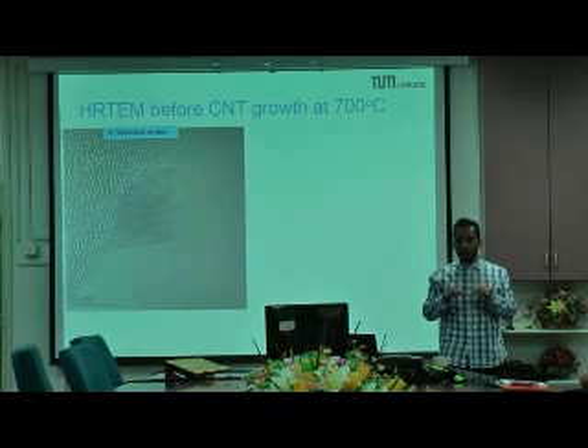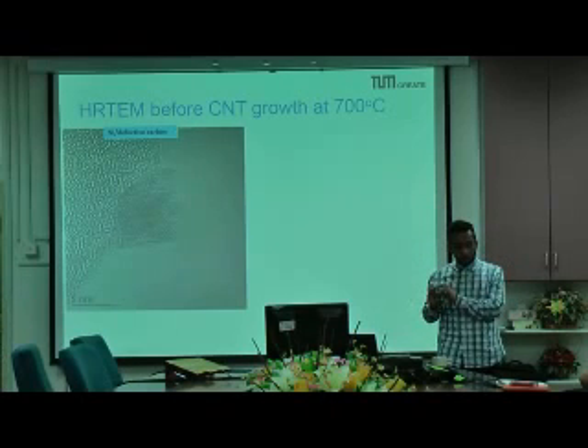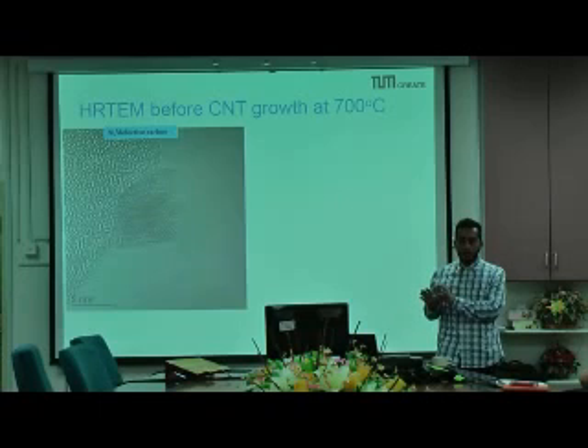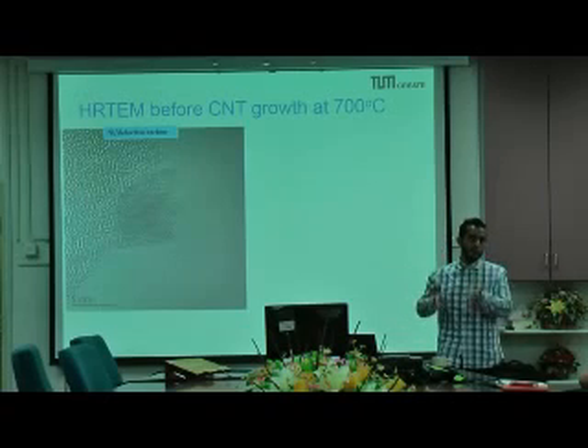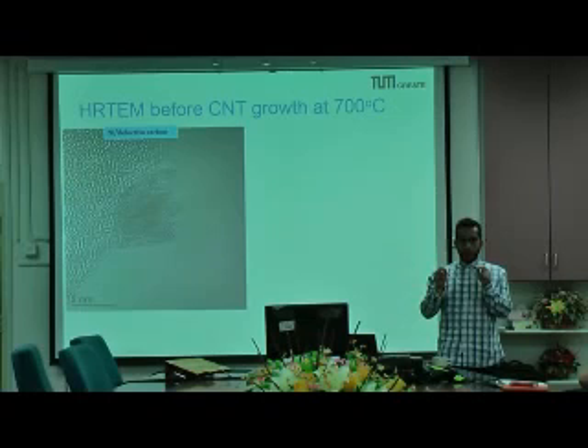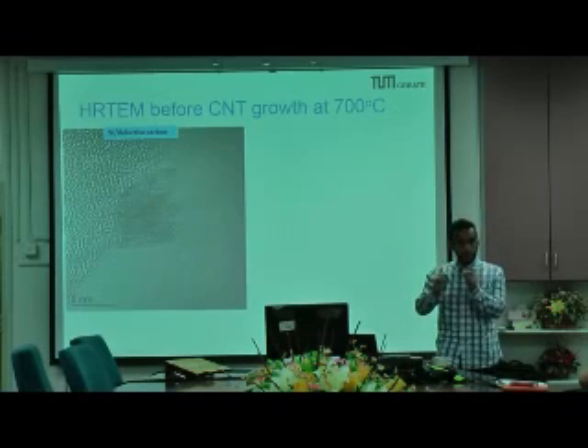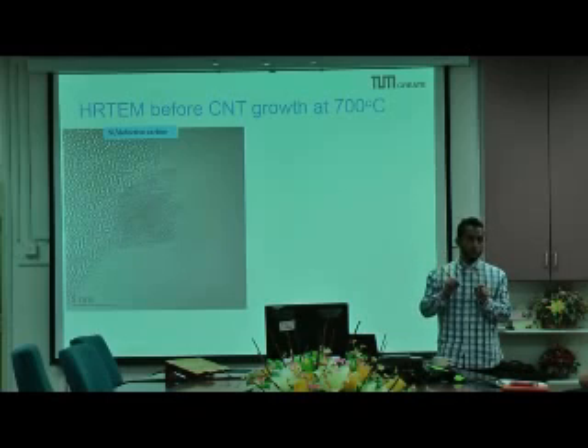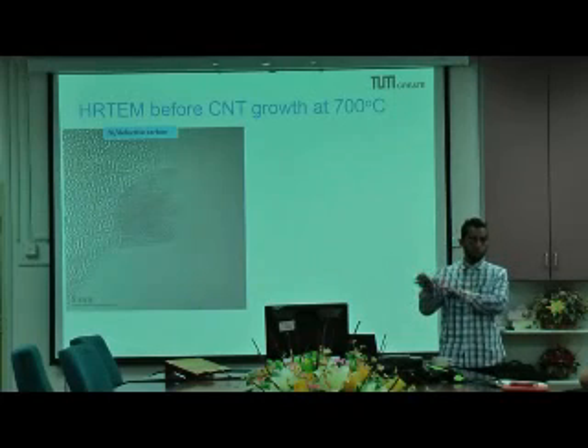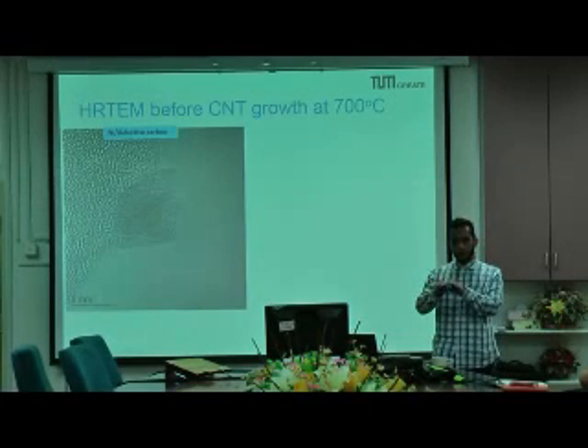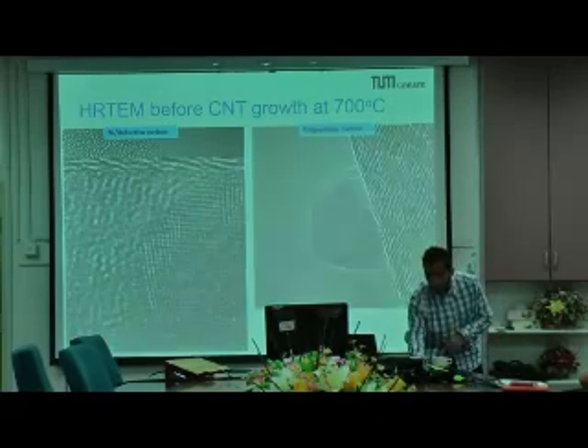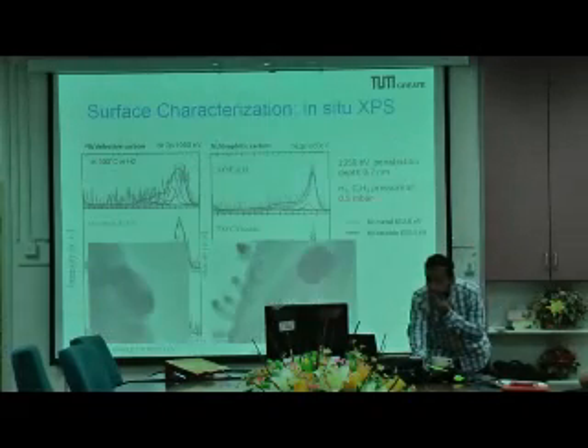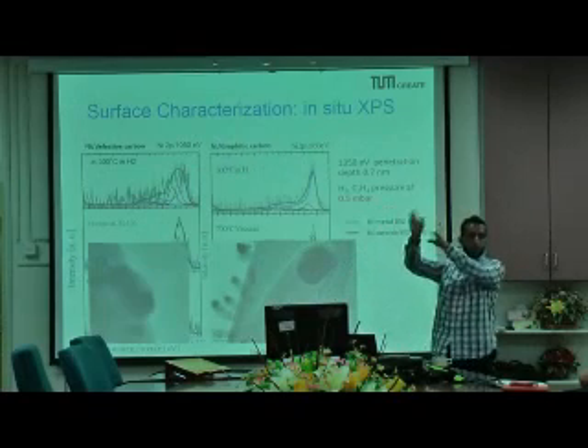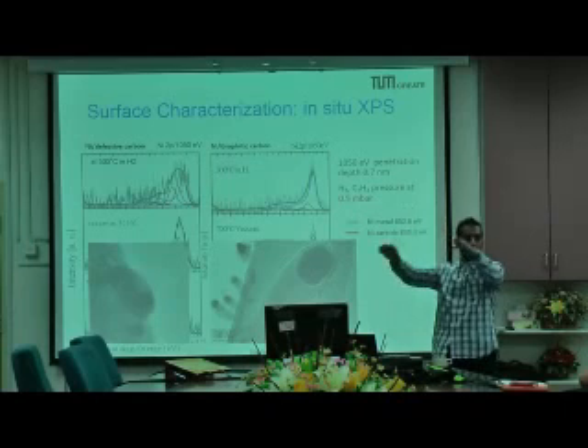That's one part. The second part is that there have been DFT calculations and Monte Carlo calculations suggesting that a specific diffusion path is required to have a very nice CNT growth. So if introducing carbon means that you disrupt the equilibrium carbon diffusion in the catalyst, the carbon will no longer follow one path. It will just go everywhere. That's what we see in the carbon deposition. So there is no orientation. The carbon is just growing randomly. It doesn't have a nice, smooth orientation.